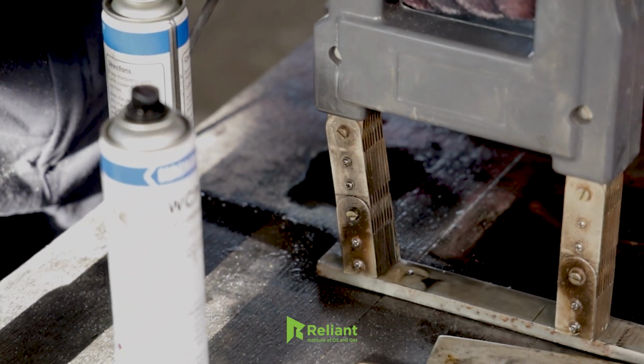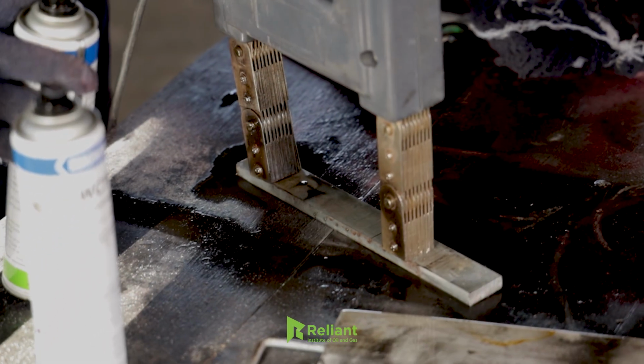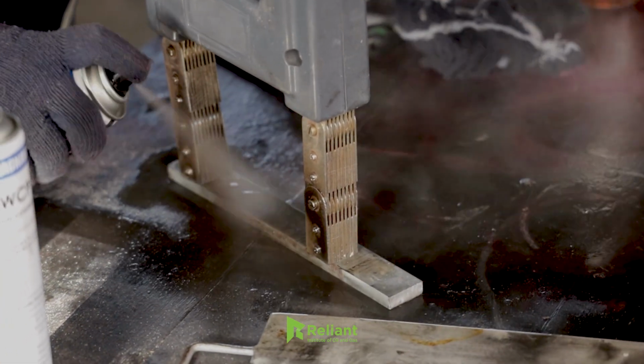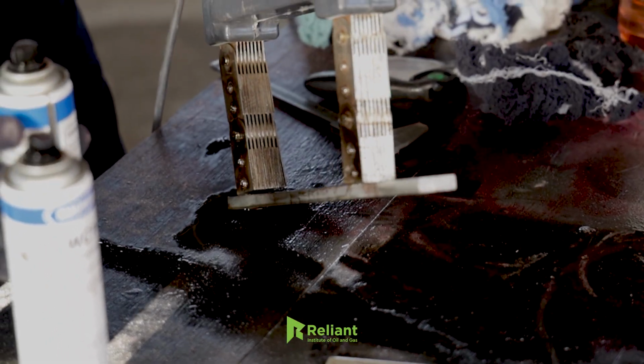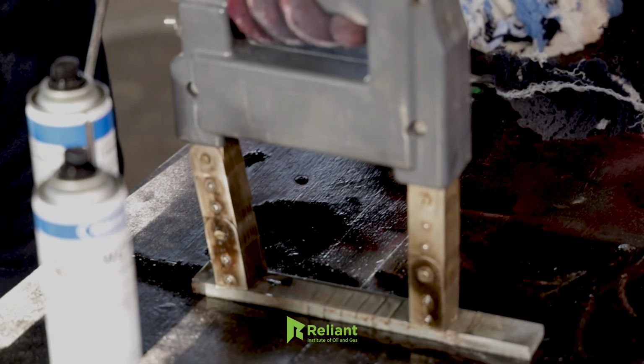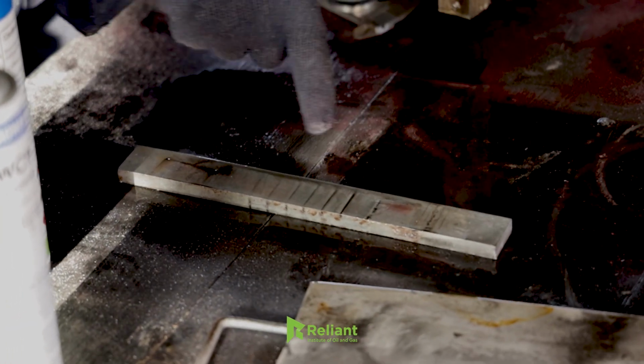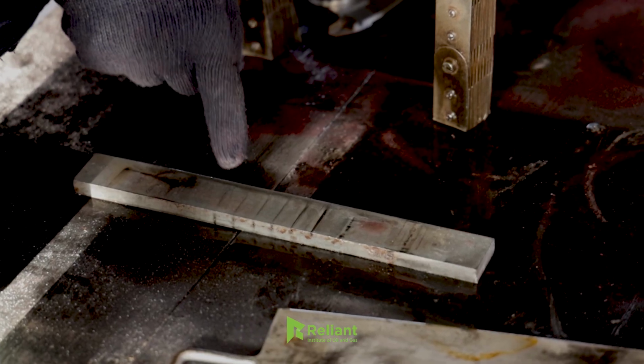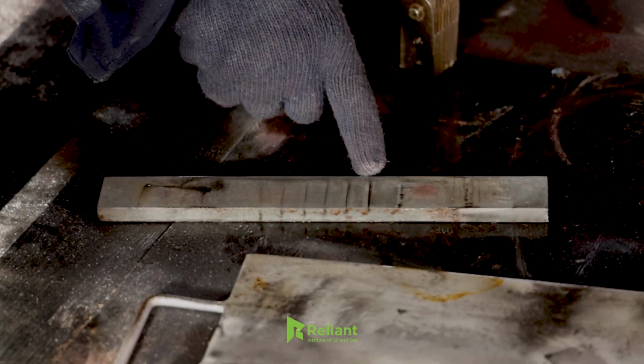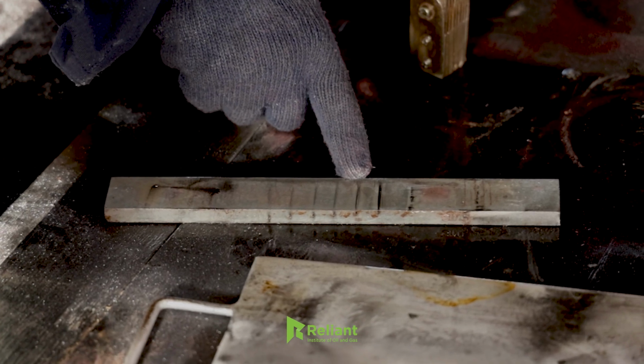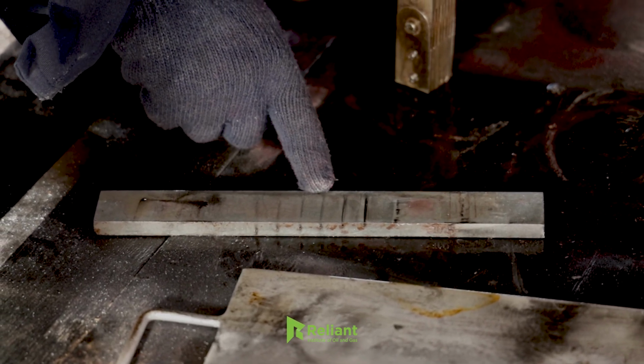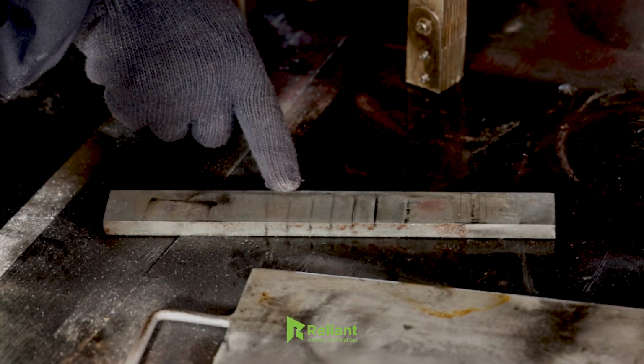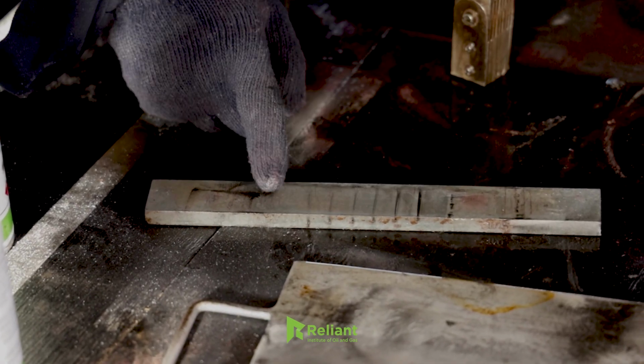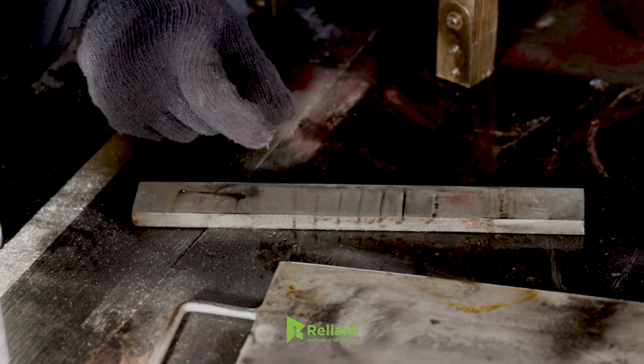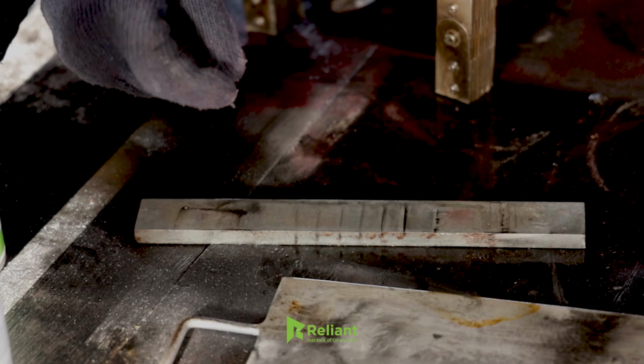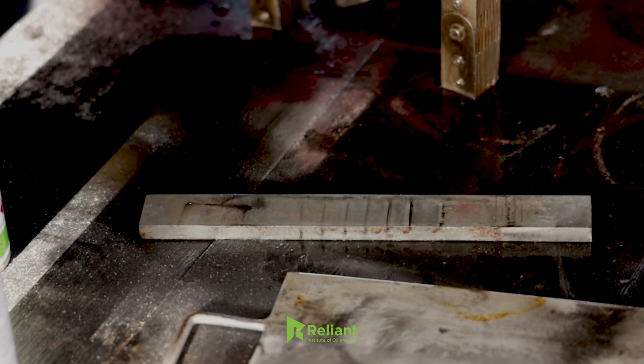Now with the DC I am applying, see, DC I have applied, there will not be any vibration with the DC, but see, based on the depth of the defect, we have 1, 2, 3, 4, 5, 6 indications we got. So this is near surface, somewhat more than 2 mm, then almost 3, then 3 to 5, 3 to 6. So up to 6 mm we got indications, but we need some more experience to clearly locate the defect, but this is also a defect. But the depth is somewhat more, that's why.